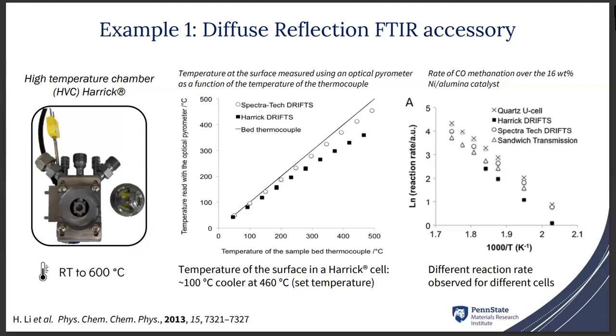If you're studying a catalytic reaction, the rate of reaction should be the same at similar temperature. This is the example of CO methanation over a 16% nickel on alumina catalyst, and we can see, depending on the accessory you're using, the rates are different.